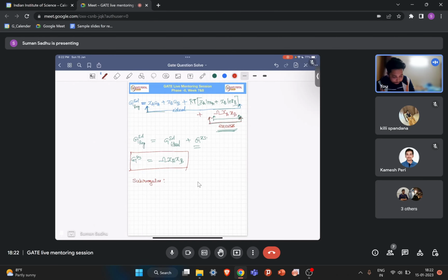I'm not going into much depth on this solution model. The only difference is that in case of regular solution, you have calculated delta H mix as omega xA xB, right? And it is assumed that omega is fixed, independent of the mole fraction of any atoms. Like let's say if you have this phase diagram, so this is 0 to 1.